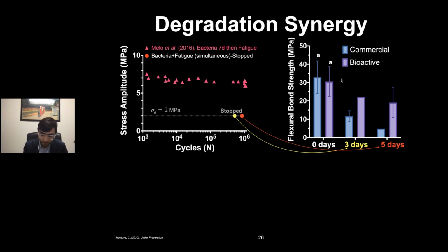So this is what we're seeing. If you prepare the sample in 0 days and break that bond of that twin interface sample, you get a comparable bonding strength between commercial and bioactive. This is more or less what people have reported in literature, around 30 to 40 megapascals of bonding strength.